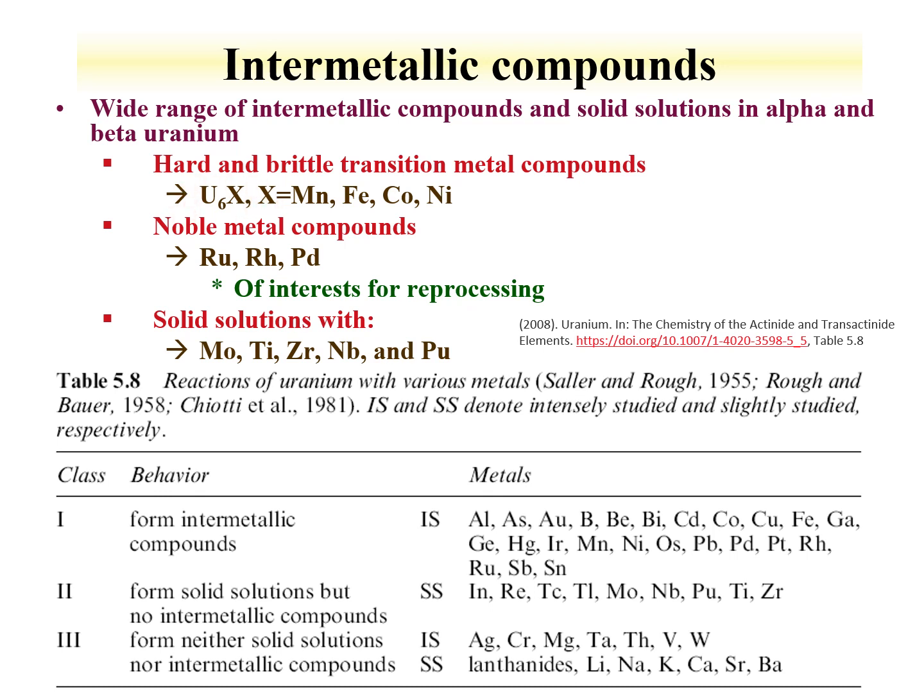So if you had uranium metal against stainless steel, which can occur in a fast reactor, and you started to have diffusion of the stainless steel into the uranium, you would change that uranium metal to this intermetallic compound. Noble metals can also form compounds with uranium as intermetallic compounds. And then as we discussed with the alloys, we get something that looks more like solid solutions.